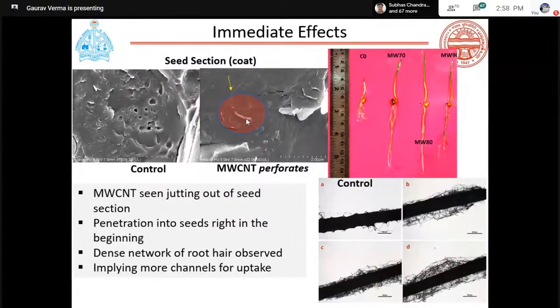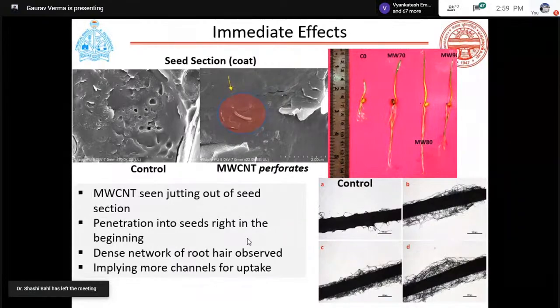And we also understand that even if you're doing a field emission scanning electron microscopy and your organism is all carbon, even if you do an energy dispersive X-ray, you might not be able to distinguish whether this is a carbon nanotube fiber or it is an integral part of the plant already. But thankfully, with the sectioning which we did, we saw a penetration of carbon nanotube into the seed, and we also saw its after effect, which were encouraging.